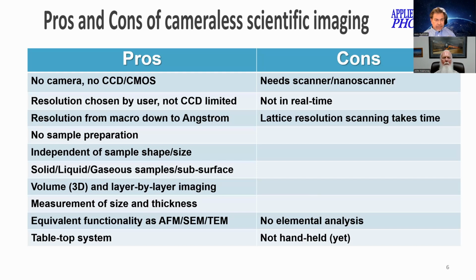Resolution range from macro to sub-angstrom. And the samples are scanned, no sample preparation necessary. It also doesn't matter what size and shape of the sample is. It can scan just about any size, any state of the sample, liquid, solid, or gaseous. Volume image, as I said, layer by layer. And measurement of size and thickness and any other metrology function that is needed for semiconductors are available here. It's a tabletop system, and it has all the equivalent functionalities of an AFM, an SEM, and a TEM combined.